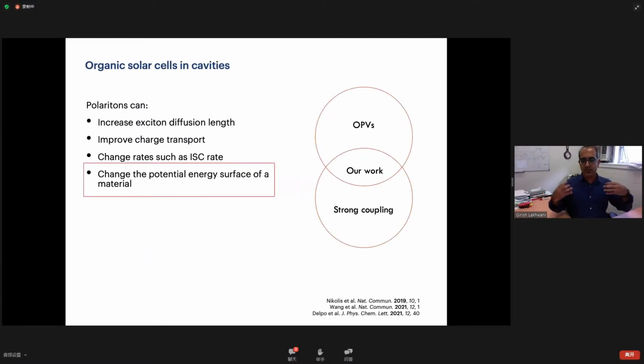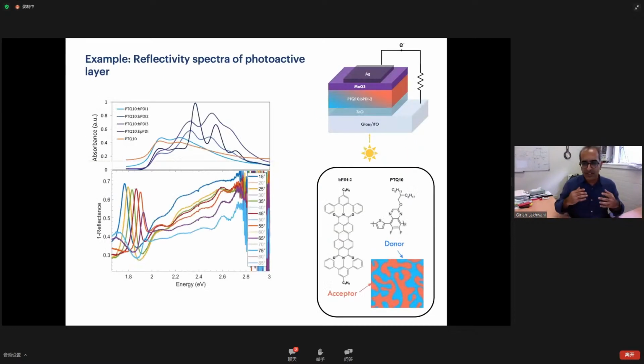The solar cell community is actually making new kinds of materials and new devices, and we are very interested in how we can use different device geometries to optimize them. One of the things we do is put them in optical cavities and change the potential energy surface. We perform these very complicated experiments, not that I'm going to go into depth, but the idea is that you make these devices with typical architectures, using typical perylene derivatives and conjugated polymers, which give them semiconducting properties. And you can make a lot more measurements.